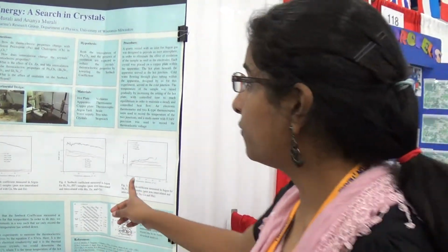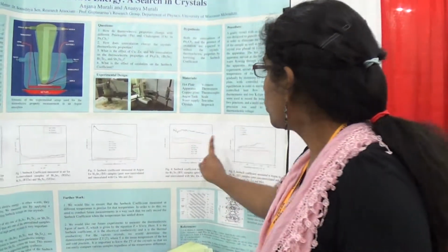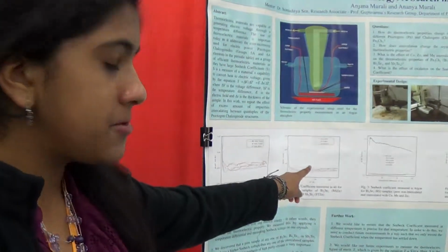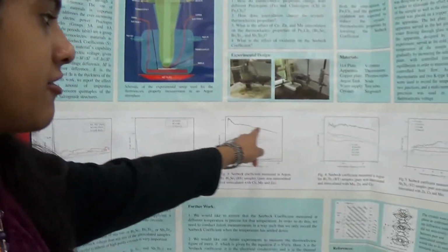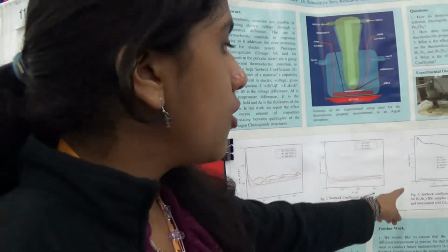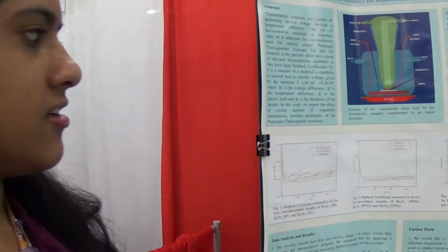As Anya mentioned before, we investigated 3 main systems, and we wanted to see which system would be best for producing a thermoelectric sample. So from what Anjana said, our second question was the effect of impurities. And as you saw in the normal room temperature examples, adding the impurities drastically lowered the Seebeck coefficient. And the same goes for the inert atmosphere. So here is our pure sample, which generated about 0.25 as a Seebeck coefficient, whereas the samples with the impurities generated almost nothing.